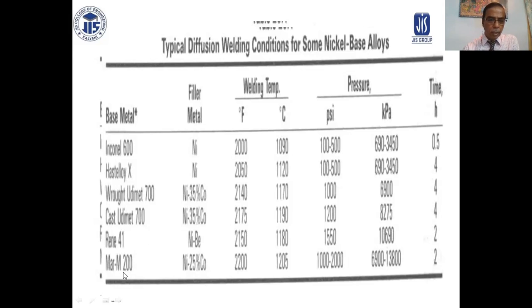So another alloy, Mar-M 200, nickel 25% cobalt. This is 1205 degree centigrade, 1000 to 2000 psi, and 2 hours required. Pressure, temperature, time: 2 hours required. So typical diffusion welding condition for some nickel-based alloy.